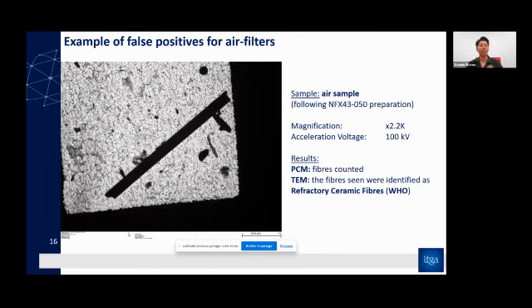And now we also have an example of a false positive. In this case, it's an air sample. And in the PCM, so phase contrast microscopy, we say that we have identified a fiber. However, using TEM, we realized that it's actually not asbestos. It's actually a refractory ceramic fiber.